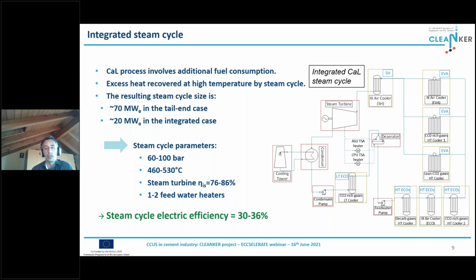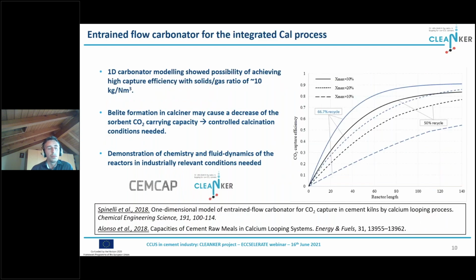In our simulation works, in general, we optimized the parameters of the integrated steam cycle and also the structure of the heat exchanger network to maximize the electric efficiency for all the configurations that we tested. Both the tail end and the integrated calcium looping configurations were simulated in the CEMCAP and the CLEANKER European projects, exploiting 0D models developed with commercial software and coupled with more sophisticated one-dimensional routines developed, for instance, in MATLAB for the simulation of the calcium looping reactors, both the tail end fluidized bed system and the entrained flow configuration.